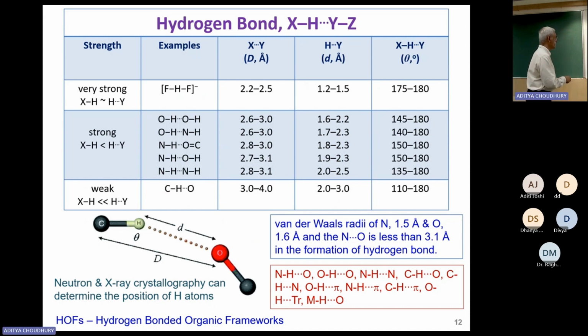So that was used, but nowadays, since you can locate the hydrogen atom and refine it, you include them in the table, and then you start to produce it. And you would see that this table contains different types of hydrogen bonds with different strengths. For the strongest one, the angle is supposed to be a straight line. That means 180 degrees. If it is 180, it is perfect. Most of the time you get around 180, about 175, something like that, even 170.